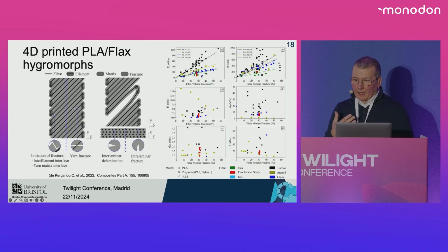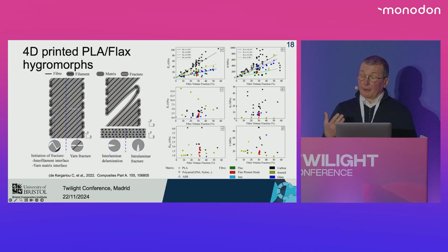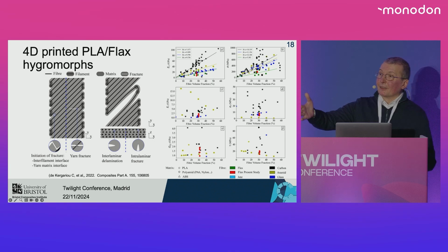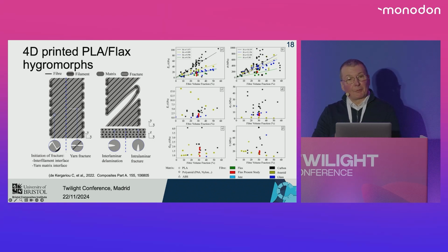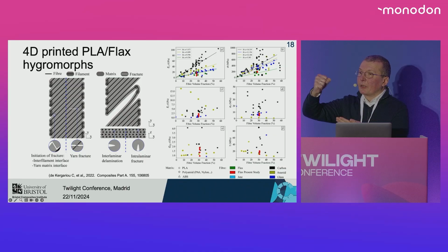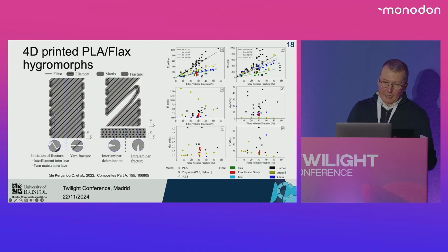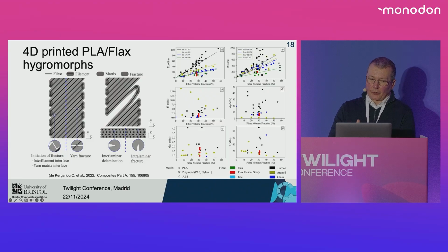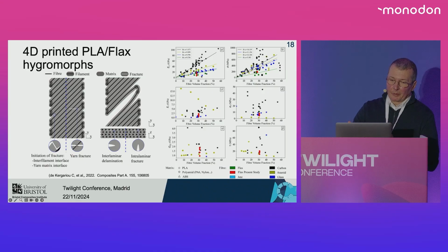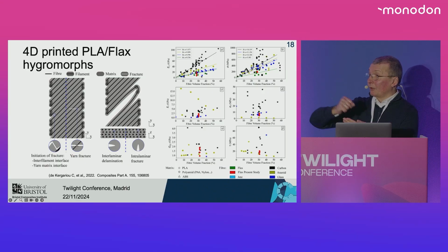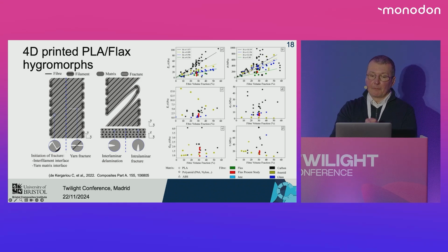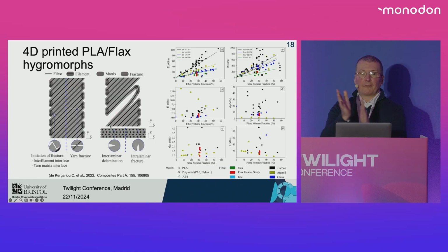Another aspect that in 4D printing is quite important is manufacturability. I'm quite happy that the previous talk was already raising some of those points, but especially when you use these types of long fiber reinforced filaments, you have issues related to the initiation of fracture in the composite at the interfilament interface. These flax fibers are made out of twisted yarns, so you have problems with the yarn matrix interface. It depends also where you need to cut the sample, and then because you need to have those types of loops in order to make a different stacking sequence for actuation, you have this type of imperfection.